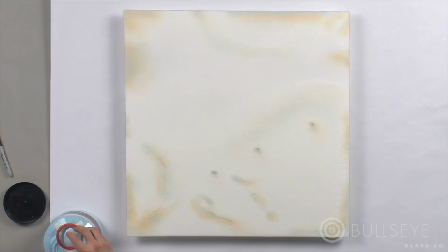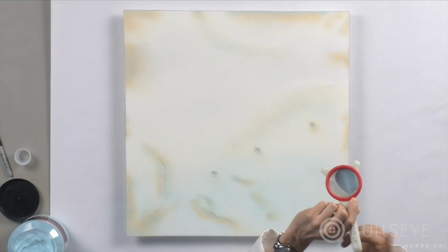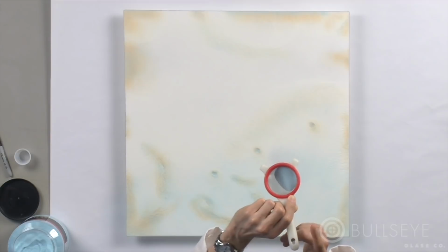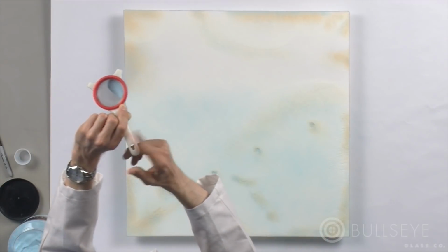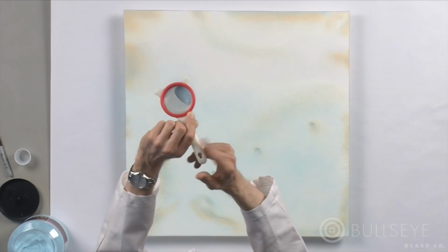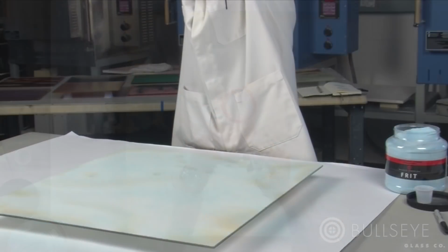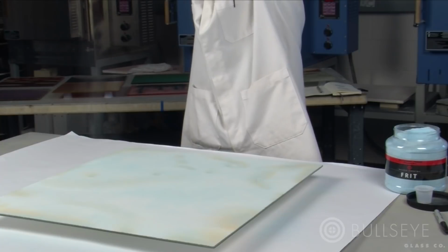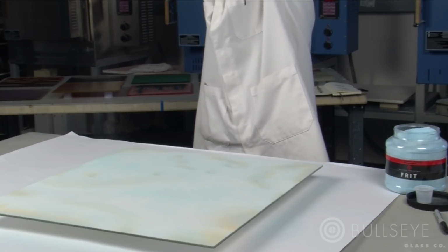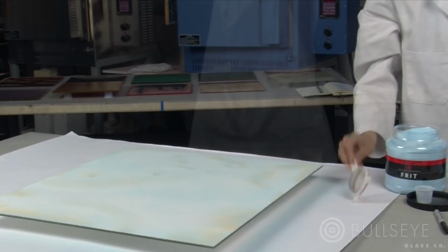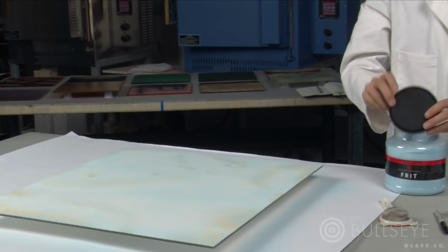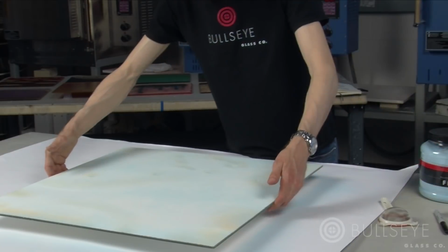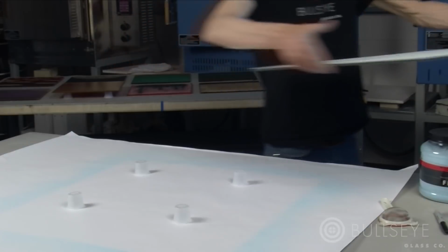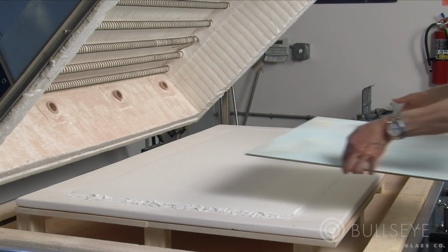And now I am going over the whole thing with 2 cups of 111608, which is the transparent turquoise powder, and that is a copper-bearing glass, so it will have a slight reaction with the French vanilla, which was set down first, which is a sulfur-bearing glass. And I end up reclaiming about a half a cup of that material.